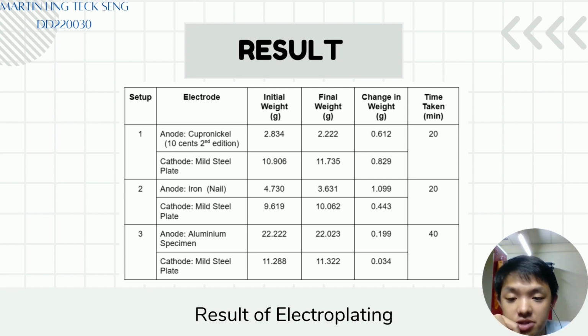But in setup 3, we can find that there is only a slight change compared to setup 1 and 2, in which the aluminum specimen decreased just 0.199 gram, and the cathode increased just about 0.034 gram, even though we increased the time to 40 minutes.